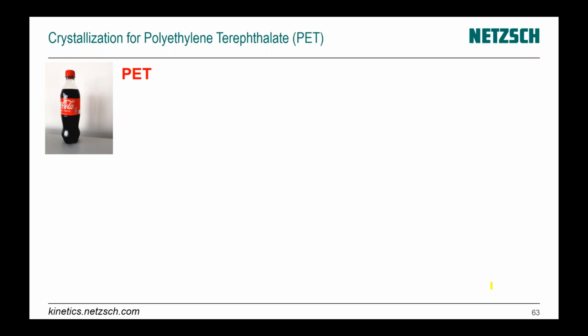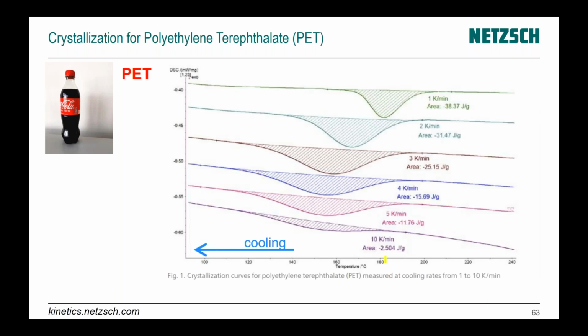Here we can make a simulation of how the material should be produced in order to be transparent. We have cooling with different cooling rates, 10 K per minute and 1 K per minute. You see for 1 K per minute the area is 38 joule per gram. For 10 K per minute it's only 2 joule per gram. It's different, it's really different.